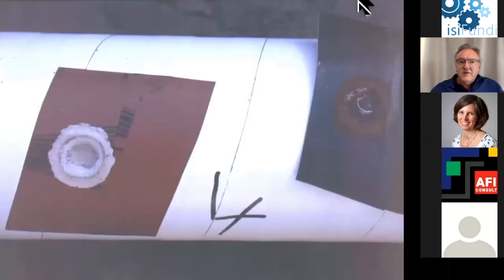Now, these bacteria don't literally eat the pipeline or the steel, but they exist under conditions where the byproducts of the bacteria cause very corrosive conditions to develop, and we can get quite severe corrosion of the underlying steel. This particular example was a situation which was considered completely non-corrosive, except that nobody bothered to test for the presence of bacteria, and perforation of the pipeline was the result.